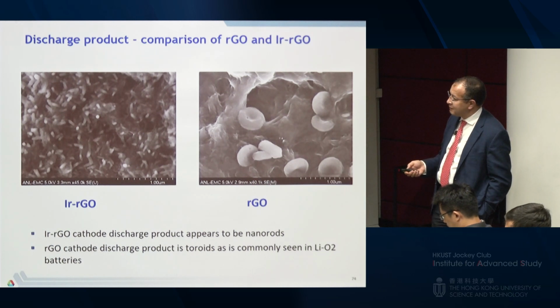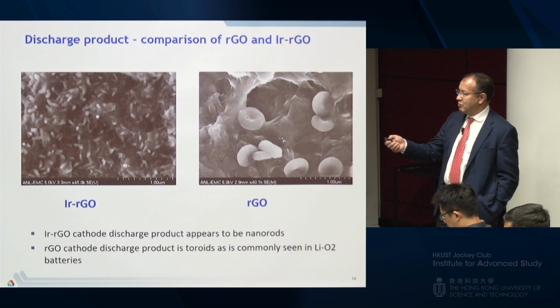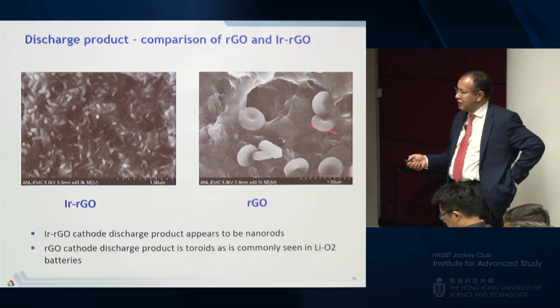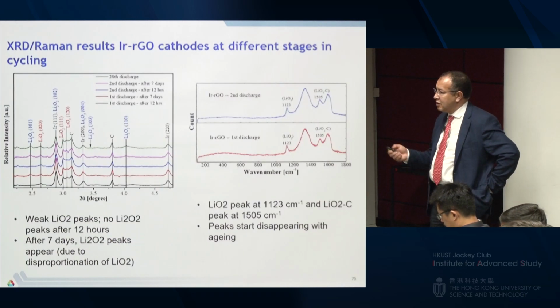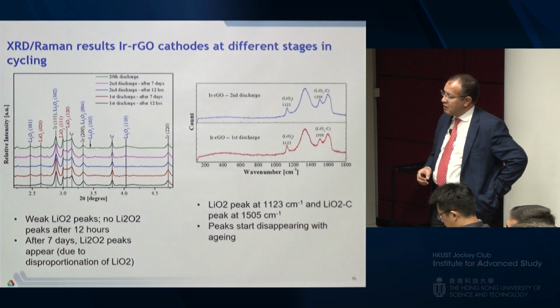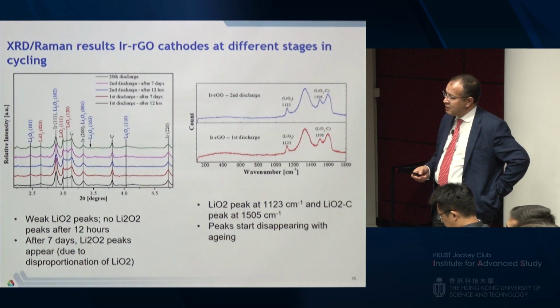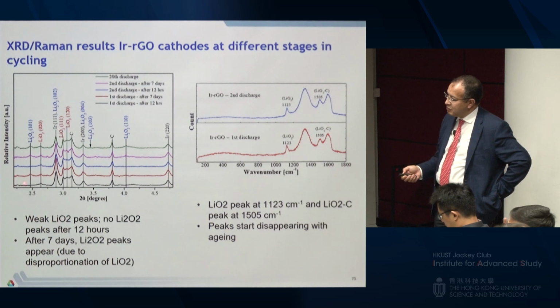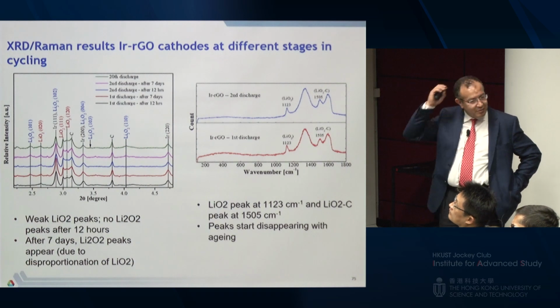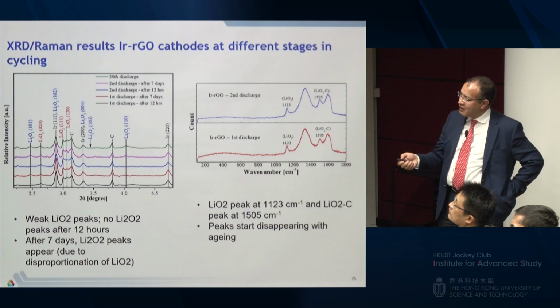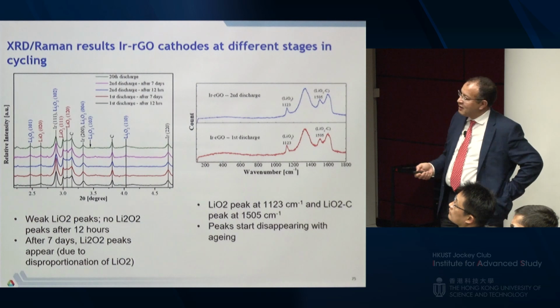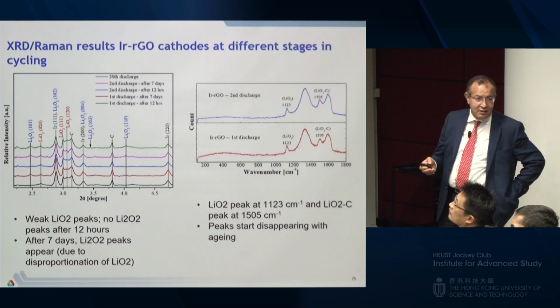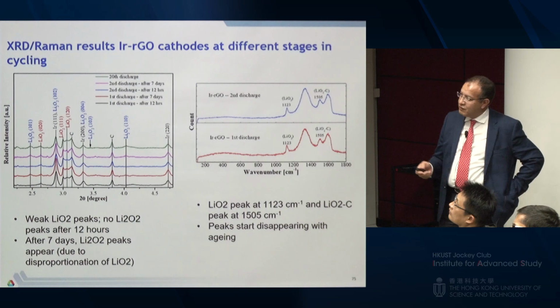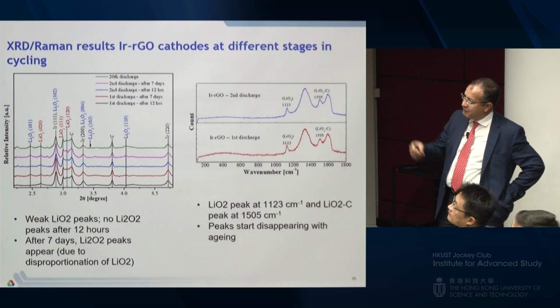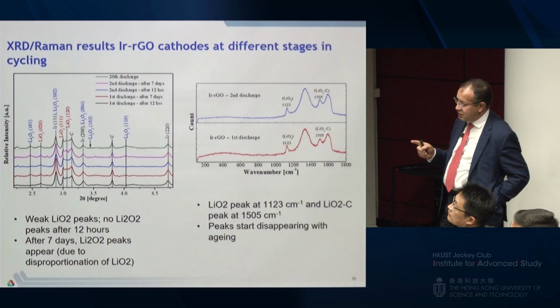is iridium. So the second thing is what type of discharge product we are getting here, because it's very different from lithium peroxide. So we applied the Advanced Photon Source, hard X-rays, and you can see we did not see the lithium peroxide, but we see a new phase, which is exactly like what we predicted by calculation, which is lithium superoxide. Since you see it, it's crystalline, obviously, and it stays stable for 7 days. It's not like, eventually there might be a disproportionation with time, so it's stable. That was an interesting thing.